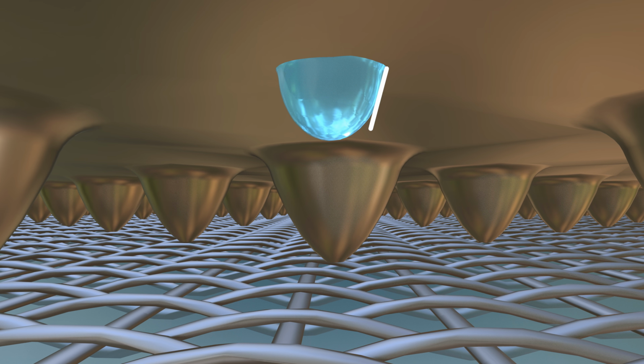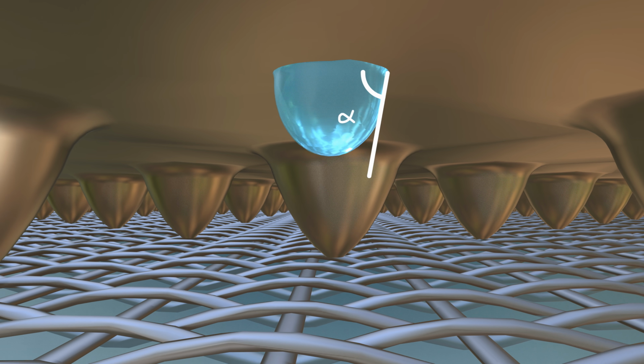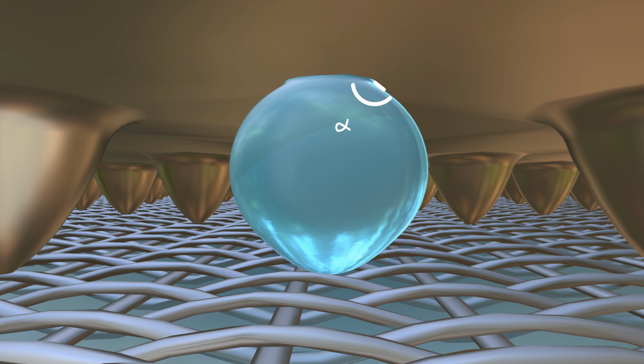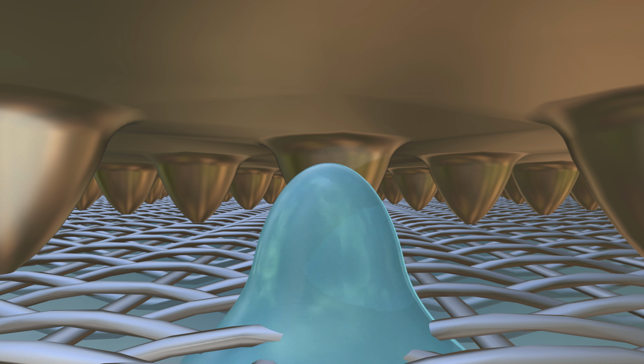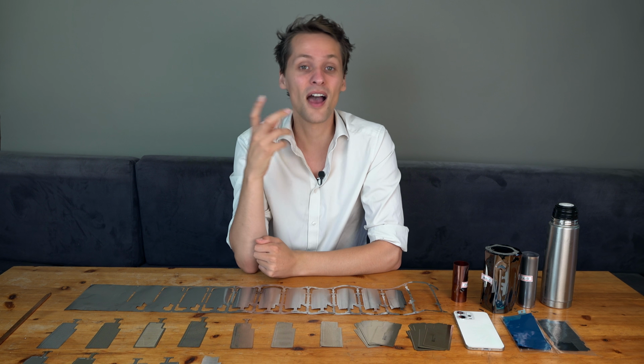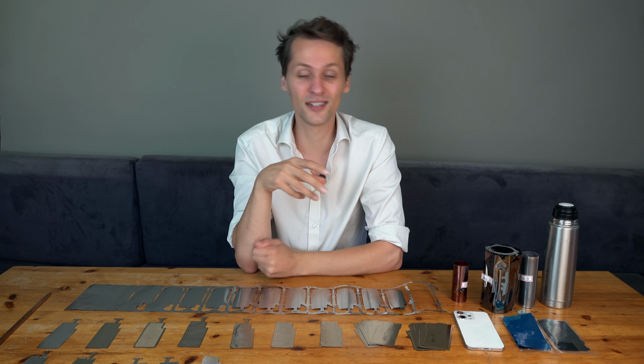It's a very good question. We have some study. By coating the top with a hydrophobic material and increasing the contact angle, droplets can actually reach the wick earlier. So you can imagine that there are some other interesting tricks you can do by changing out hydrophilic or hydrophobic coatings on different parts.